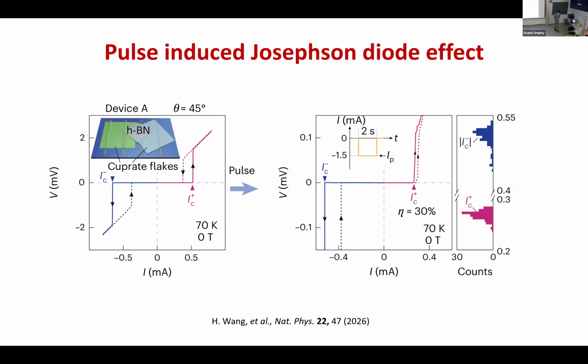And this is just the final page. Diode effect: we could also induce a diode effect in the sample if we apply some current pulse. It's very reproducible. We introduce this diode effect, where there is an asymmetric critical current. If you just raise the temperature above Tc and cool down, you can go back to the symmetric case. And if you send the current pulse, you can again have the diode effect.